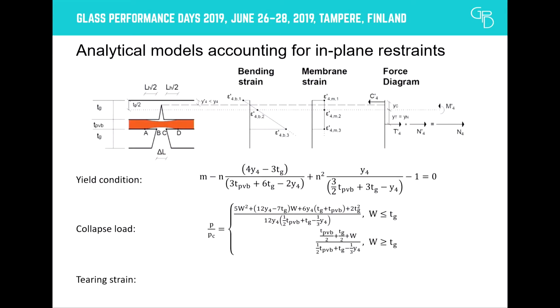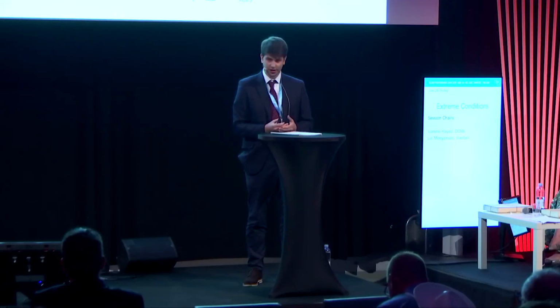Finally, we can define the collapse load at which tearing occurs. This can be achieved by equating the bending and membrane strains with a tearing failure at high strain rates that was previously defined. It should be noted that this only refers to tearing strain and does not account for cutting from the attached glass fragments.